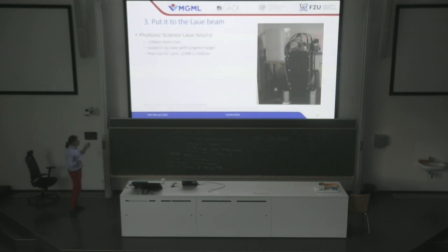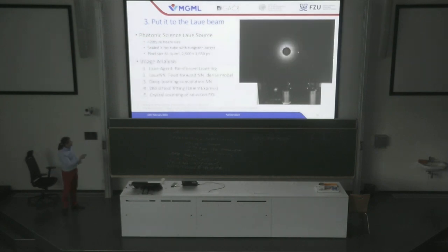Then we are using a commercial Laue diffractometer, which uses X-rays shining on the sample, and then we see these spots, and this is actually the reciprocal space. This is the Fourier transform of the real space where the atoms are sitting in the lattice of our crystals. And for analysis of these patterns we are using several methods. We are currently determining which method is the best.